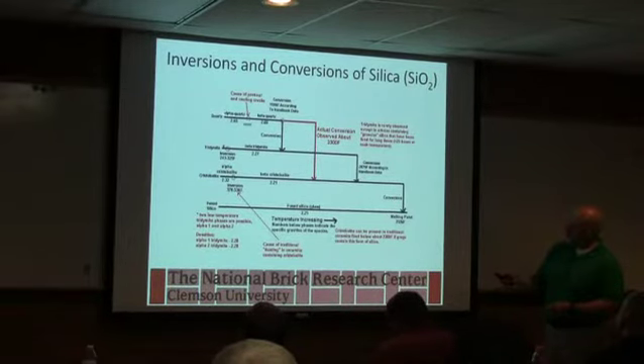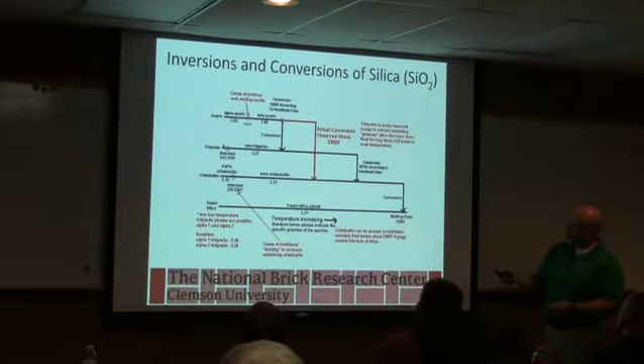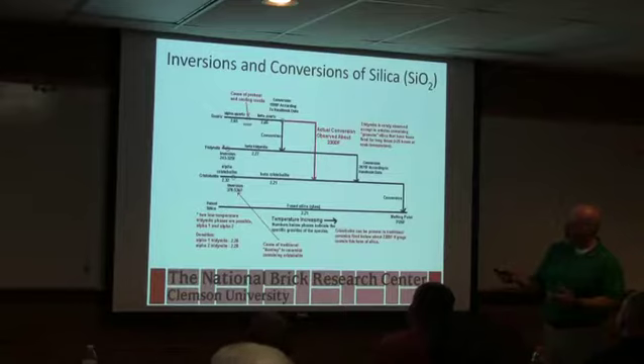So what happens is on heating, I get to about 1066, and I go from this low quartz to the high quartz. And generally in brick, this is all we see. We don't get hot enough to go to cristobalite. When I cool it off, it goes the other way.